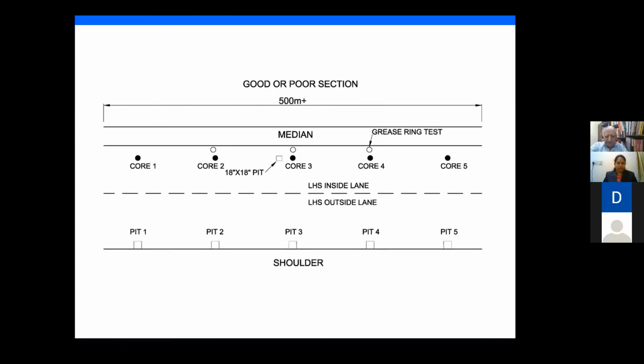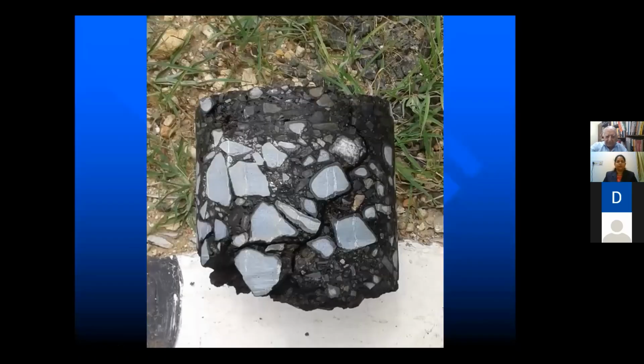So once I take all these cores, like a full depth core here, in this case there is a bituminous concrete layer on the top, and there's a DBM, dense bituminous macadam, below it. This core was taken on the crack itself, so you can see the crack is propagating from the bituminous concrete through the DBM. So I take a full depth core and then I analyze them in the laboratory for density in all the layers, bitumen content, dilation, all those kinds of things. I verify those, and then I compare those values between the good and poor section.